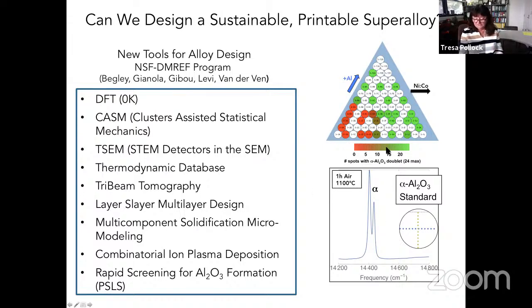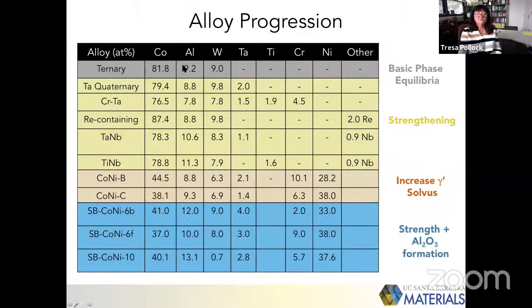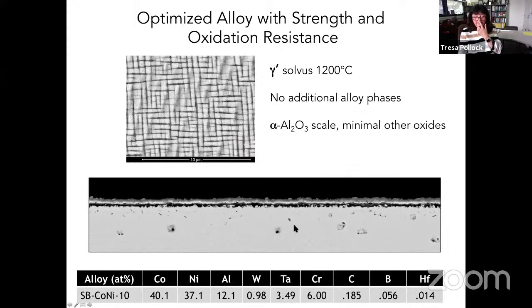And so bringing together all of these tools, we went through a few generations of materials and then basically ended up with some alloys that are a near balance between cobalt and nickel. Here's the composition shown at the bottom, and then aluminum for formation of precipitates. And so with the combinatorial experiments, we end up at this final composition that I show at the bottom. You can see when this material is oxidized at 1100 C, there's a layer of alumina here.